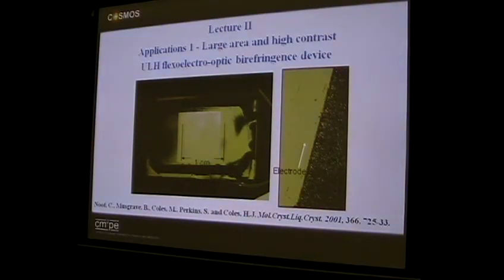You do have fluorine as an atom, but when you talk about cyano, this is a bigger group. We change from cyano to fluoro to lower the transition temperatures. The materials show much lower temperature phases. So we went from the biphenyl material at 205 degrees Celsius isotropic to nematic, down to about 100. And then when you start making mixtures, you can go down to minus 20, minus 30.